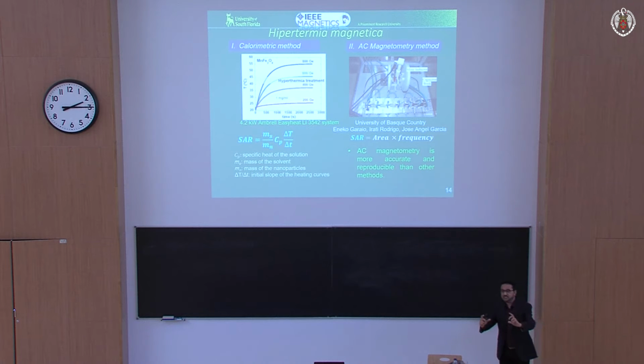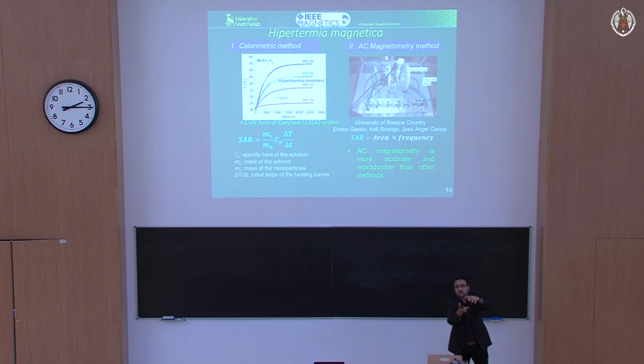So we can optimize this so that we can have a large slope, heat it fast, and then hold the temperature in that window. There is no reason to overheat it. Of course, at low fields, you won't get to that. So you need to come up with this simple condition of optimization where you can come to this 40 to 45 degrees Celsius and hold it for about 40 minutes for the treatment, okay?